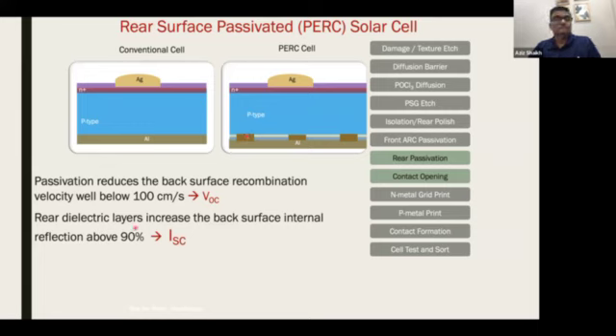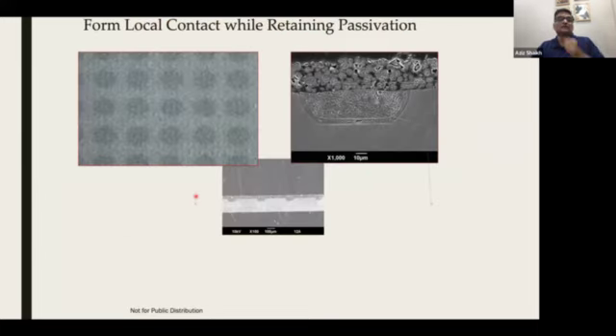I talked about the back surface recombination velocity with BSF alone being 500 centimeter per second, but with the back surface passivation, it drops to 100 centimeter per second. That drop in recombination velocity improves the open circuit voltage as well as the short circuit current. Both of them improve, and the efficiency of a solar cell is nothing but VOC times ISC multiplied by fill factor, which is an indication of how efficiently you are collecting. That is more about the contacting, the metallization of the cell. Since both of them are increasing, you get improvement in efficiency.